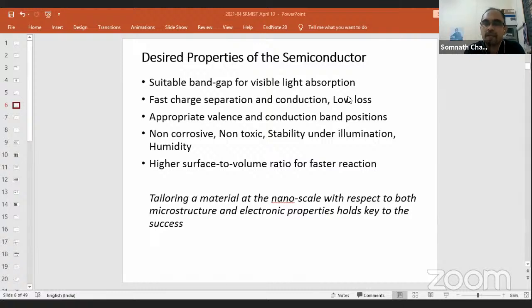Even if I have materials with suitable band gap, the problem comes in two ways. Either the material is not stable in water, or let's say I am trying to run a photocatalysis process where my electron is in the conduction band and the hole in the valence band. Now the electron requires a certain energy to initiate a reduction process. The hole requires a certain energy to initiate the oxidation process.